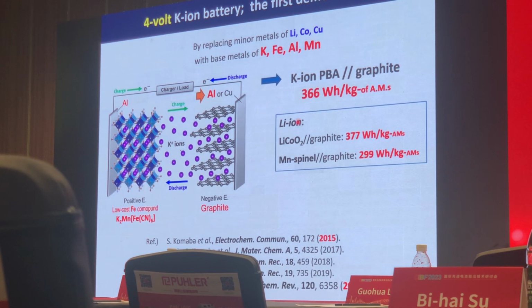Actually, based on manganese iron hexacyanoferrate complex compound for the positive and graphite for the negative electrodes, and also we can use an aluminum current collector, we can demonstrate higher or comparable energy density for potassium ion cells to the lithium cobalt and manganese pair lithium ion battery. And please note that the potassium cell, which is based on potassium ion, aluminum, and manganese, is free from lithium, cobalt, and copper, which are costly metals.